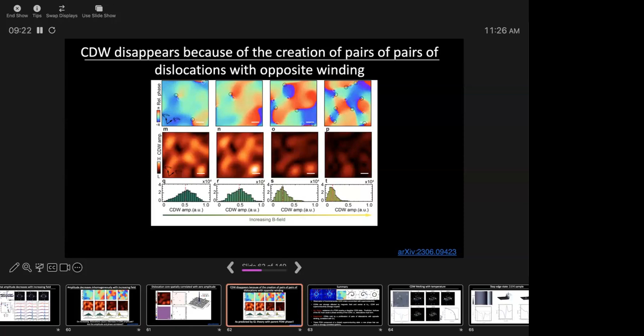That's a really good question. I don't know that we've been trying to answer that question. One thing we try to do is look at the PDW directly with a normal tip, and see if we can see the oscillations in the superconducting gap and what's the size. Sometimes we think we can see oscillations that are much bigger, on the scale of 50 or 100 microvolts. If you take a line cut along the atoms, you can see oscillations at twice the atomic distance with a pretty large amplitude. So I'm not sure. One possible answer might be that the PDW energy scale is bigger than that 10 microvolts. Another possibility, I actually don't know.